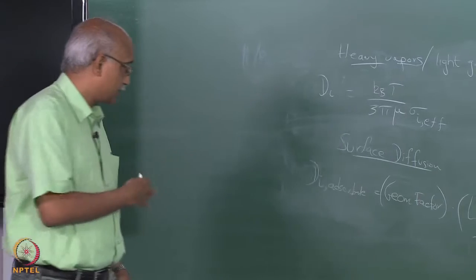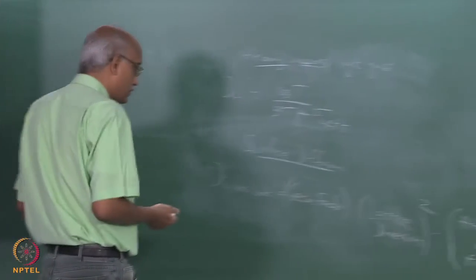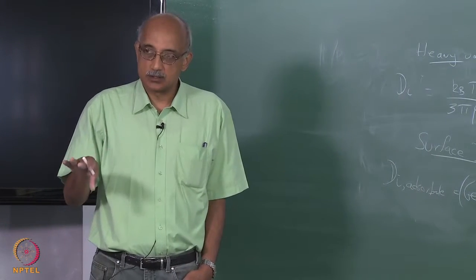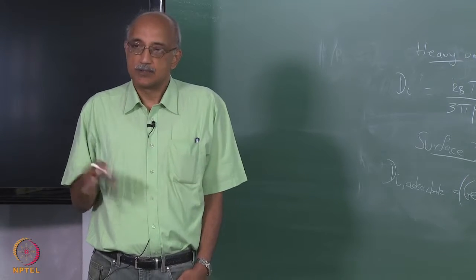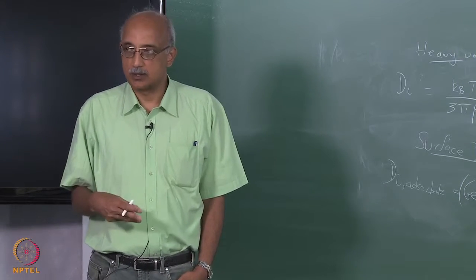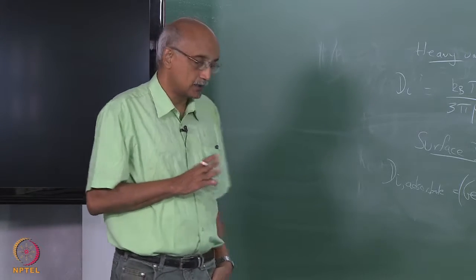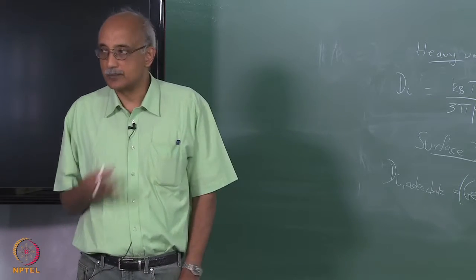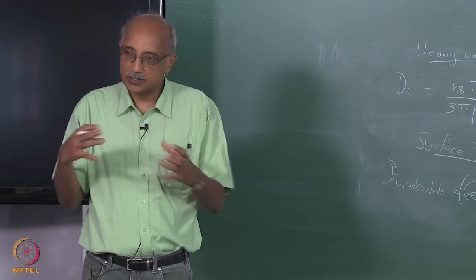Now, if you look at this expression, the interesting thing of course is that the geometry plays a huge role. For example, if you have features on the substrate that make it difficult for diffusion to happen, that can have an inhibiting effect on the diffusion process. On the other hand, if you have certain well-defined diffusion pathways to begin with, it will actually speed up the diffusion process. So, all this is clubbed into this geometric factor term.